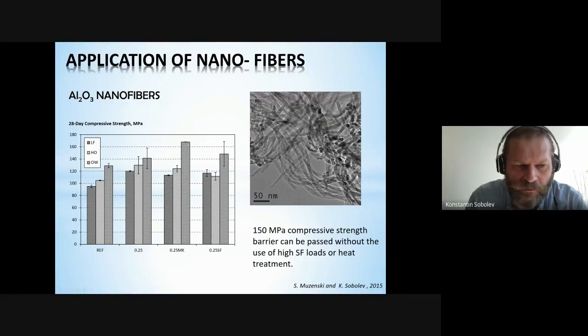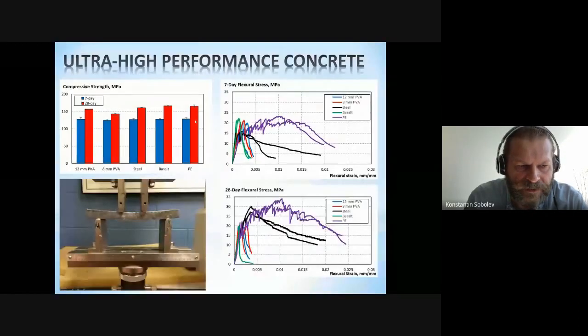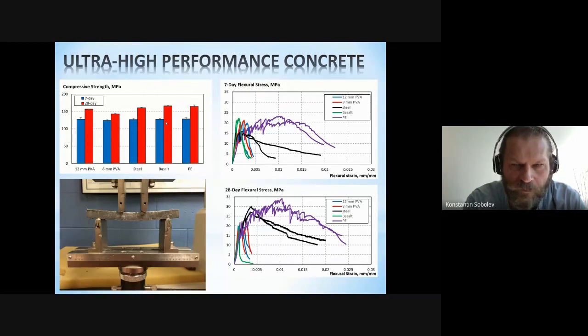So in this way, we can easily produce statistically higher strengths of more than 150 megapascal, relatively easily. So you can see that such high strength, ultra high strength cementitious matrices are useful for ultra high performance concrete, and can be easily combined with different types of fibers.